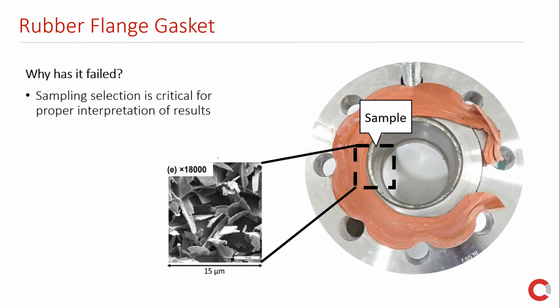In their test, and this is where their claim was based on, they only sampled a small area from the inner diameter of the gasket. This area was showing some degree of damage, as can be seen in this image. However, later on, we concluded that this was attributed to direct contact with the fluid in the pipes rather than a defect in degradation of the gasket.